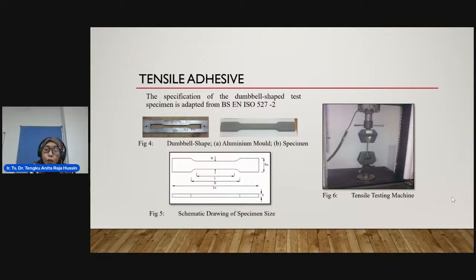So the adhesive was mixed manually until well blended, approximately for 5 minutes. The adhesive that has been prepared was poured in the aluminium mold at 4 millimeter thick. A plate was placed on top of the mold for even surface, and weights were put on top of the plate to flatten the surface, and the specimens were left for 10 days for curing before test. You can see the machine here.